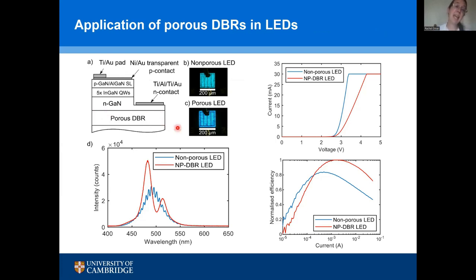Now, because we can etch the distributed Bragg reflectors at the wafer scale, we can essentially just treat them completely like a substrate, just as if we had any other gallium nitride substrate we wanted to put into our growth reactor. And then we can grow our structure of the LED on top with P and N type layers and quantum wells. And we can then fabricate it in entirely the normal fashion. We grew 2 LEDs simultaneously, and we fabricated the LED structures in exactly the same way.